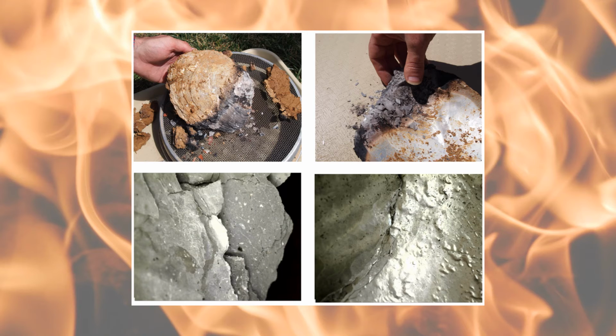And when we took off the mud, it did indeed protect the shell that wasn't exposed. And the very thick hinge section, you could just literally crumble away with your fingers. It was completely disaggregated. And under low power microscope, as you see at the bottom, this was looking at that fractured surface after crumbling away the very burnt shell. You can see how lamellar that is, all of those different layers stacked one on top of the other.